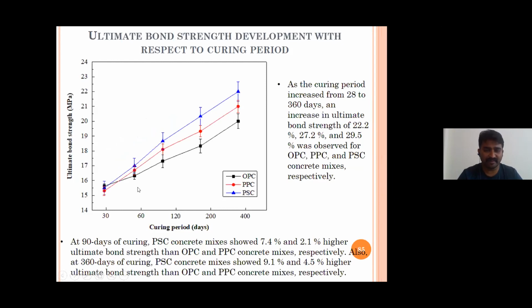Same trend you can observe in bond strength also. Ultimate bond strength at 28 days: OPC, PPC and PSC concretes have similar ultimate bond strength. As the curing period increases, 56, 90, 180 and 360, we have doubled the time. So PSC concrete achieves more bond strength compared to OPC and PPC. The main reason for this is that PSC concrete's Blaine fineness is very high compared to PPC and OPC. So that's why the finer the material, the more the reaction, and at the steel concrete interface, PSC concrete shows better ultimate bond strength compared to OPC and PPC.